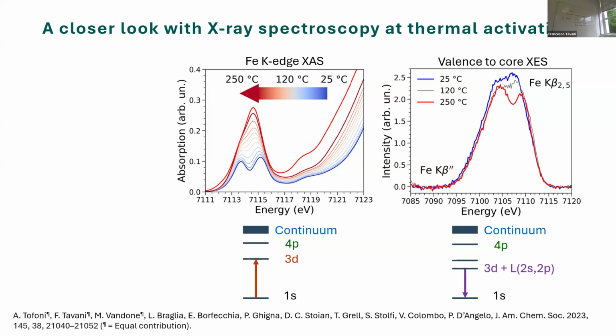And you can see that the edge energy shifts towards the left, and this is because the energy required to extract the photoelectron is less, because there is a progressive reduction as a function of thermal increase. And you may see that two peaks present in the pre-edge in the spectrum of the pristine MOF progressively coalesce into a single peak. This means that there is a consistent structural change involving the iron local environment.